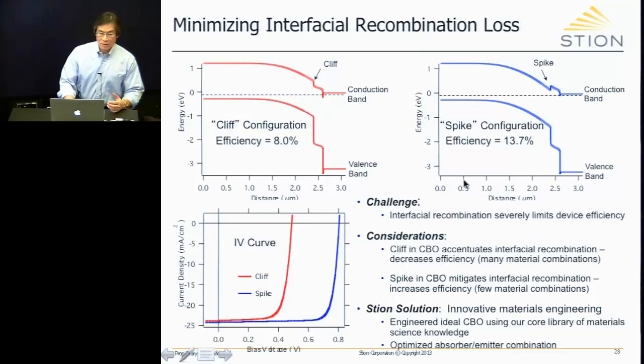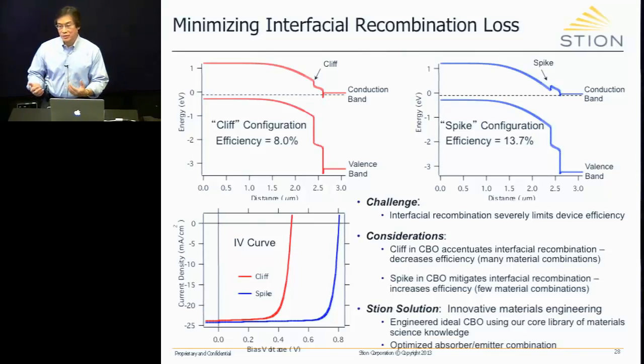And then the question naturally becomes, how do you control the conduction band offset? You control it by the emitter that you use, by looking at what the electron affinity of the emitter happens to be, and how it would match up with that of the absorber itself. So we will go through a number of different emitters to control the conduction band offset, to control the efficiency by controlling the interfacial recombination.